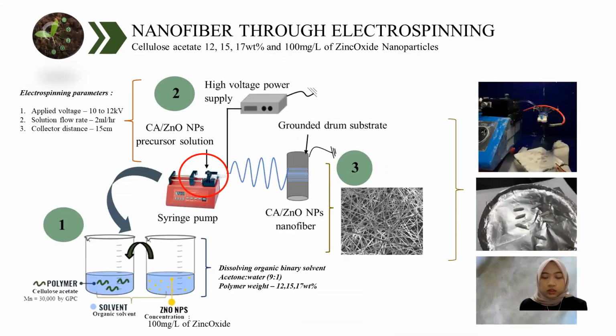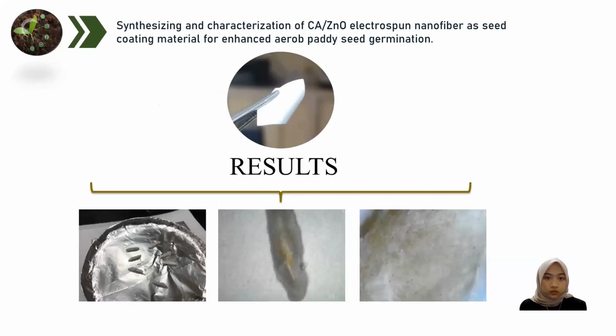So this is the method that we are utilizing, and here the seed coating method is a layer by layer coating method, where we electrospin the fiber on the aluminum foil, and then we place the seeds onto the fiber and produce more fiber on top of it. We punch them out within a 5 mm scale range, and this is the image of the fiber coated seeds that we have been producing.